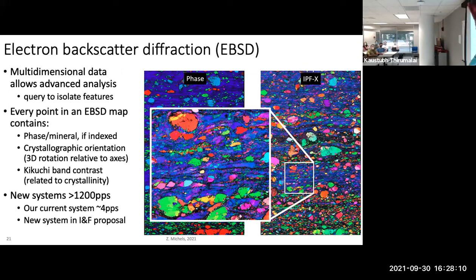This particular map was collected by my colleague Seth Krickenberg at Boston College, who has one of the newer EBSD systems. And this is almost a full thin section and contains just over 12 million data points. So our current system here can collect about 4 points a second. The system that we're trying to upgrade to collects about 1,200 points per second on geological samples. On metals or something, you can get up to 4,000 points a second. So the hope is that we're going to be able in the near future to make maps like these of any rock.